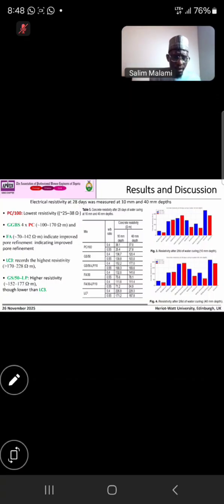Then FA has 140, 142, even greater than PC, but is less than that of GGBS. So this indicates improved pore refinement. When we say there are pore spaces in the concrete, we want those pore spaces to be tortuous, non-accessible, closed. So if less chloride ions pass into the concrete,